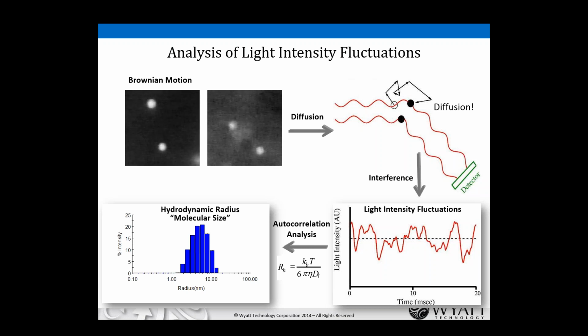Finally, we apply the Stokes-Einstein relation, shown here, to determine from the diffusion coefficient and the temperature and viscosity an effective measure of size known as the hydrodynamic radius. The hydrodynamic radius represents the size of a sphere that diffuses in solution at the same rate as the molecules or particles that you're looking at. And that results in the graph that we see here on the left side, which gives us percent intensity of the scattered light as a function of size.